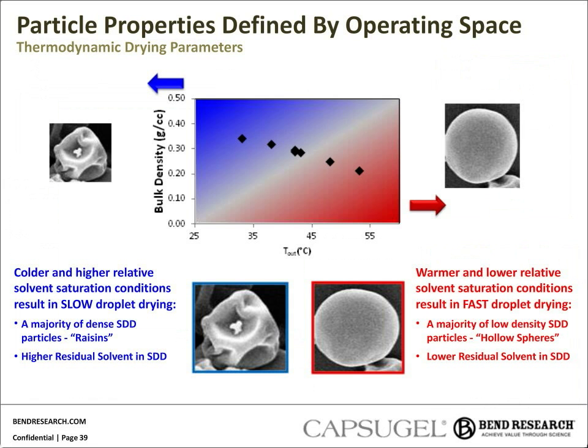Okay, the SDD product attributes like density or compressibility often correlate well to the outlet temperature and relative saturation at the dryer outlet. Due to the nature of the film-forming polymers used in SDD manufacture, we see a skin formation on the droplets immediately after the solvent evaporation begins. If the drying rate is slow, or if the spray drying parameters are cold and wet, this skin remains pliable as the particle forms, and the resulting SDD has a shriveled raisin morphology with high density and low compressibility.